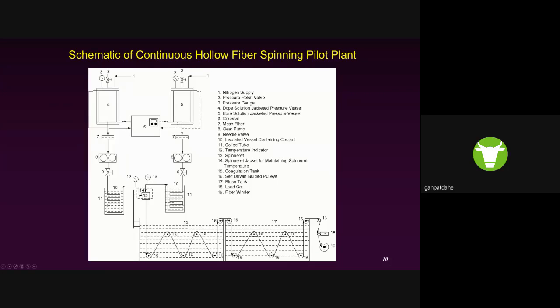In the first tank, we call it the dope solution tank, where the polymer solution is prepared, around 15 to 30% polymer solids, and the minimal viscosity of this solution should be around 10,000 centipoise. Then there is another solution called a coagulant, also called non-solvent, and both solutions pass through the spinneret. The spinneret is one of the keys to producing this hollow fiber membrane. It has an annulus and a bore, and is called a tube-in-orifice spinneret. Through the bore the coagulant flows, and through the annulus the polymer solution is extruded.